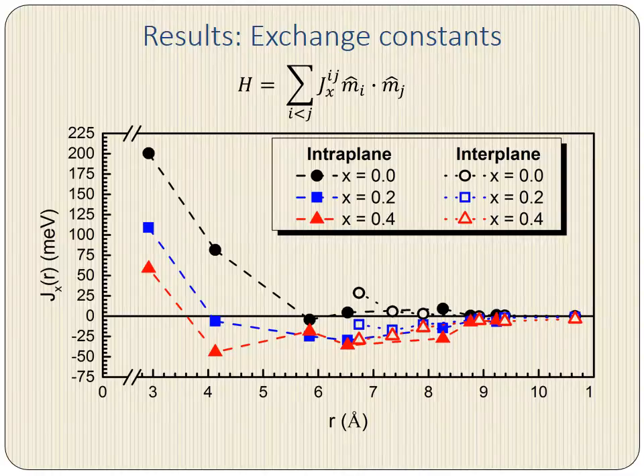Now we move on to the meat of our results, the exchange constants. The exchange constants, which are defined in the Heisenberg model, describe both the nature and strength of the magnetic coupling. A positive exchange constant means that we have antiferromagnetic coupling, whereas a negative exchange constant means that the coupling is ferromagnetic. Furthermore, the constant J here is actually the product of a coupling constant and the local manganese moment squared, which is how we obtain units of energy.